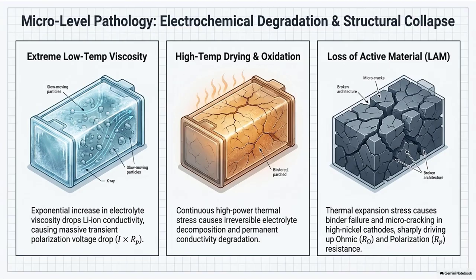It becomes electrically isolated. It's in the battery, but it can't participate in the circuit anymore. This is especially critical with modern high-nickel cathodes, right? We are seeing a massive push across the industry toward NMC 811, so that's 80% nickel, 10% manganese, 10% cobalt, mostly because of the incredible energy density. But that density comes at a structural cost, doesn't it? Oh, absolutely. High nickel cathodes are incredibly energy dense, but they suffer from severe structural instability at high states of charge and high temperatures. They're fragile.